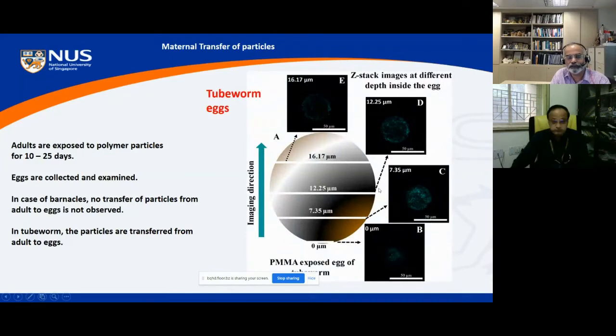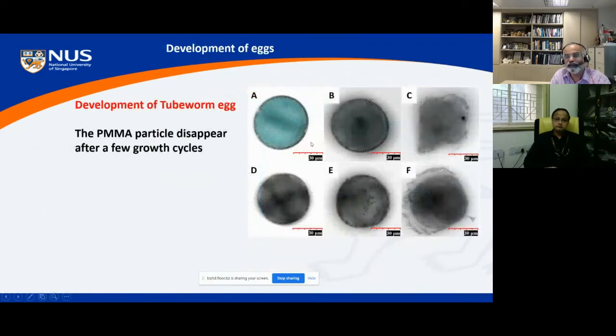So here are the tube worm eggs. Again, we are doing the cross-section. So you can see different cross-sections, different levels of illumination. That means the particle concentrations are different at different parts of the eggs. Yeah, so these lighted spots are actually individual polymer particles. And then another interesting thing we just found out is that when these eggs are developing from day one to day five or day 10, they tend to have this ability to release these particles from the eggs.